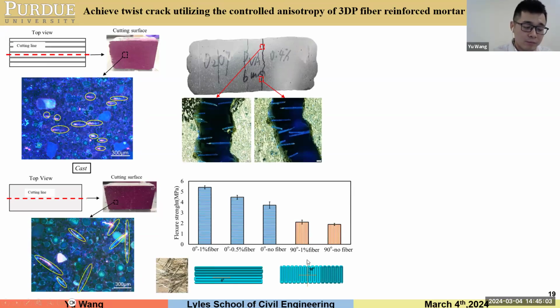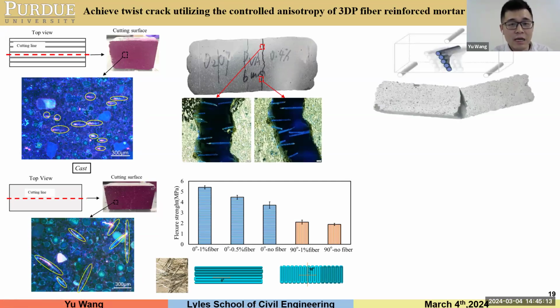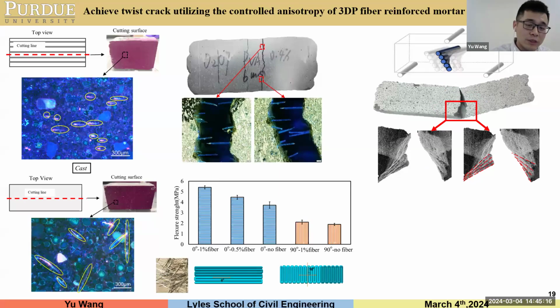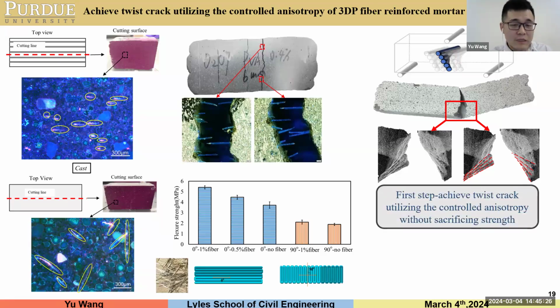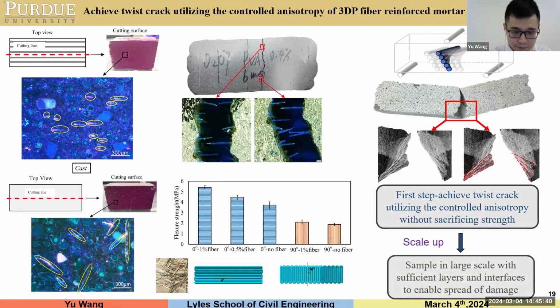For the 90-degree and 0-degree samples, if we test in a three-point bending test, we get significantly different flexural stress. Taking advantage of this high anisotropy, we printed our sample with the Bouligand architecture, and we successfully replicated the key twist cracking mechanism at small scale. And we didn't sacrifice the strength. We didn't intentionally make the interface weaker. We just used the normal printing process and achieved the key mechanism. The next step is to scale it up to a large scale, where we will have enough layers and interfaces, so we will promote micro crack development to improve the toughness and energy absorption capacities.